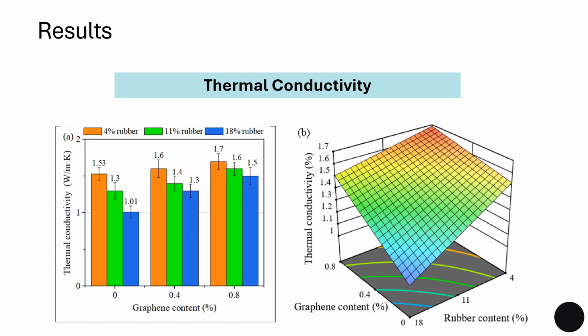On the other hand, in terms of thermal conductivity, with the same combination, 18% of rubber and 0.8% of graphene, we can get acceptable thermal conductivity, which is 1.5, which is smaller than the control. It means with the combination of rubber and graphene, we can get two benefits. We keep the compressive strength higher than the design strength. At the same time, we get low thermal conductivity compared to 1.7.